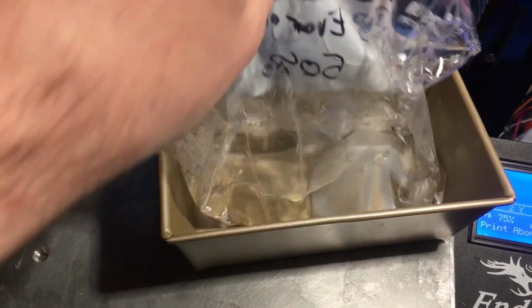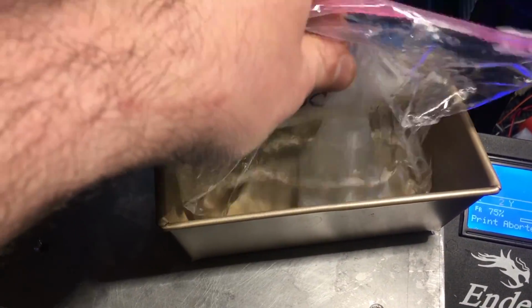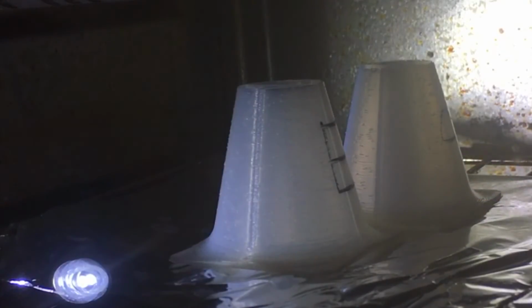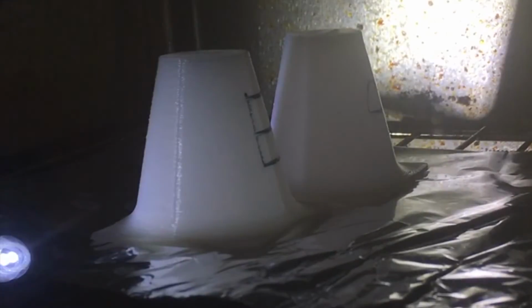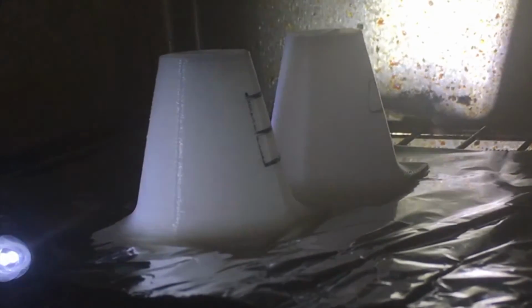Next up, we have the cones, which I printed out to kind of simulate a heating funnel that would be sitting near the hot end or something like that. For this, I just did the control versus taking the ethanol at 50% concentration and cooking it on the 3D printer build plate at 45 degrees for 1 hour. Now, this test was much less interesting to look at, but this was more about distorting the shape or preserving the shape than it was about catastrophic failure or anything like that.